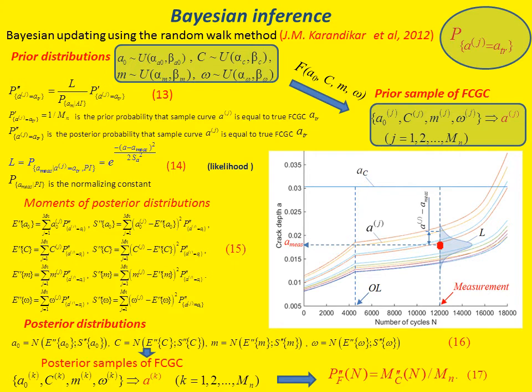After that, we can draw samples from these updated Gaussian distributions and construct a posterior set of fatigue crack growth curves. Then the posterior probability of fatigue failure is estimated according to equation 17 as the ratio of the number of posterior sample curves that cross the AC line within the interval from 0 to the current value of n to the total number of curves in the sample.